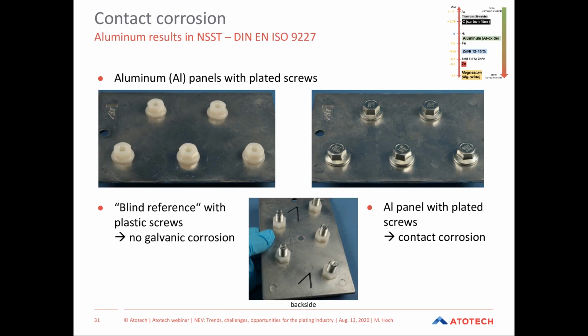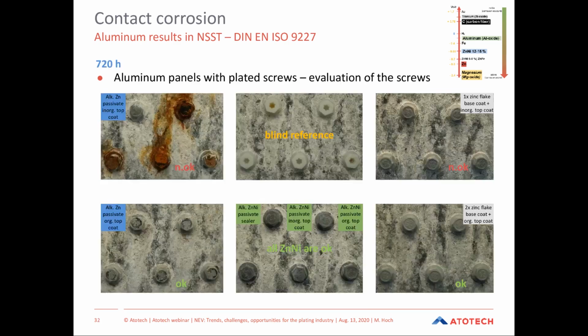The next contact corrosion test we did is with aluminium. So we had aluminium panels and screwed in plated screws. We had one blind reference, which you see on the left side. This is with plastic screws, so here no galvanic corrosion can occur. And on the right side, you see the aluminium panel where the plated screws were put on, where we expect the contact corrosion. All screws, again, were fixed by plastic nuts on the backside.